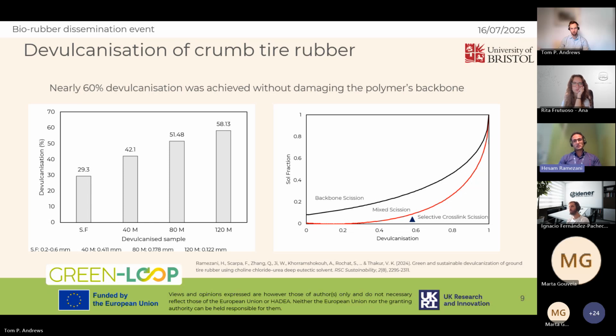But during devulcanization, there is also the potential to break the backbone of the polymer, which is basically considered as the degradation of polymer. In order to evaluate that, we use Horikx formulation and equations. And as you can see on the sol fraction devulcanization plot, there is a red curve, and the region below the red curve belongs to selective crosslink scission, where the crosslinks or the sulfur bonds that hold the rubber chains together are located. And in that region, if the calculations show we are there, we are basically selectively cleaving and breaking the crosslinks. Next, please.